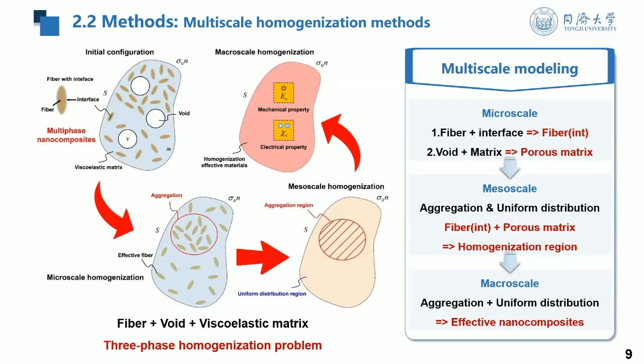Here is the theoretical framework for the multiscale homogenization method. First of all, here we consider two aspects. One is the carbon nanotubes as short fibers, with an imperfect interface between the carbon nanotubes and the matrix. On the other hand, we also consider the void. The void we introduced into the matrix controls the stiffness and the deformation of the sensing materials.